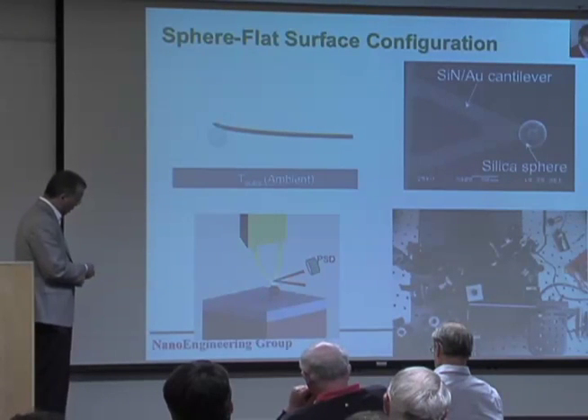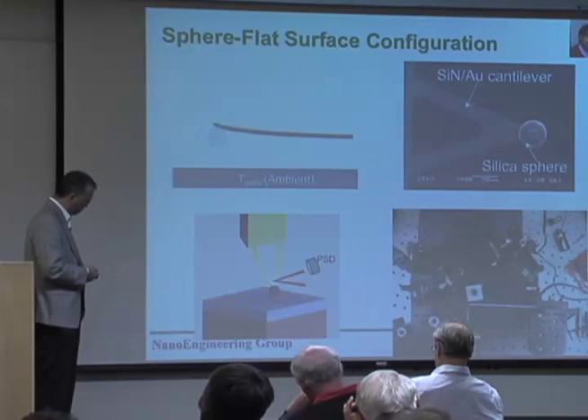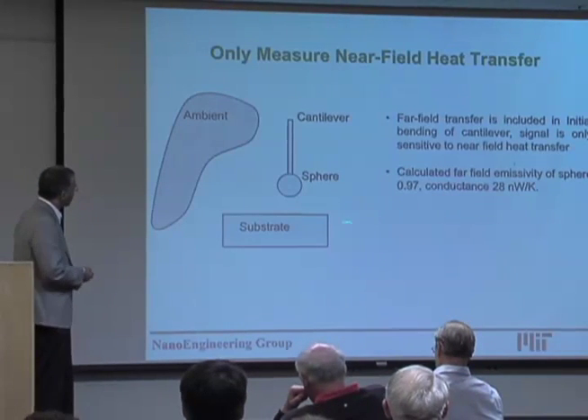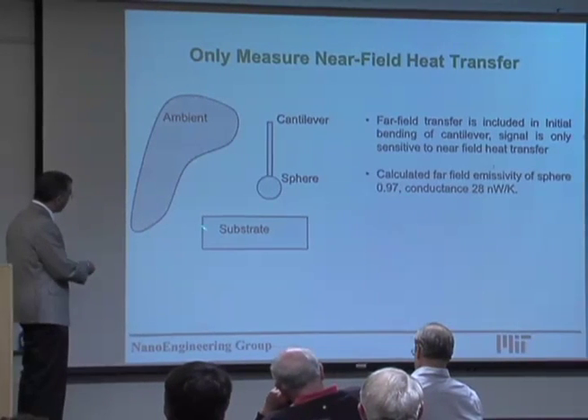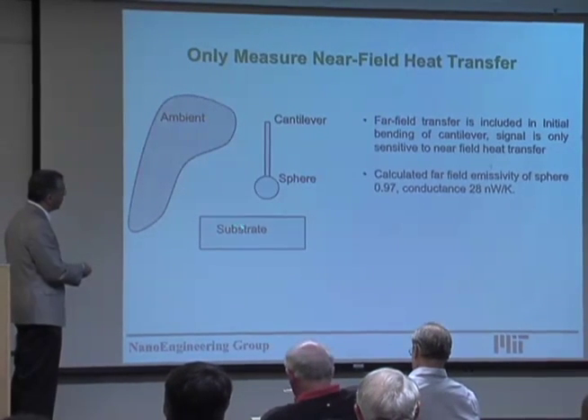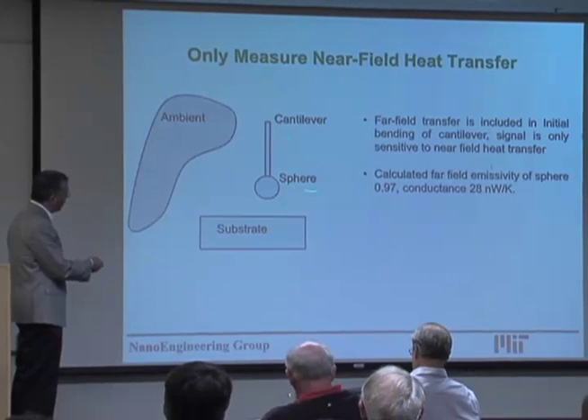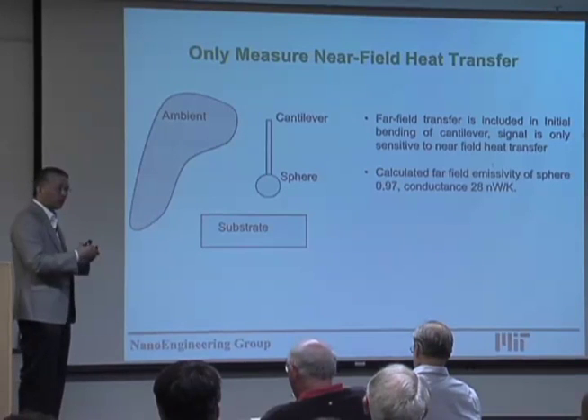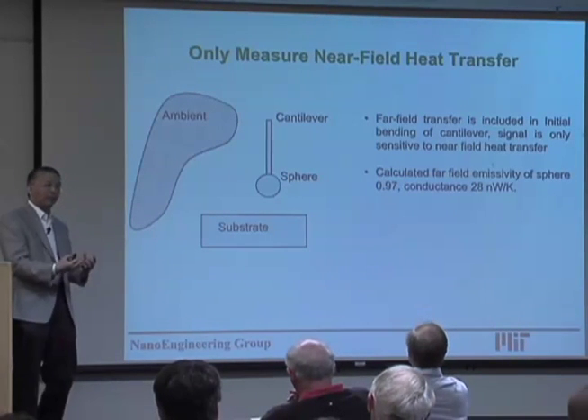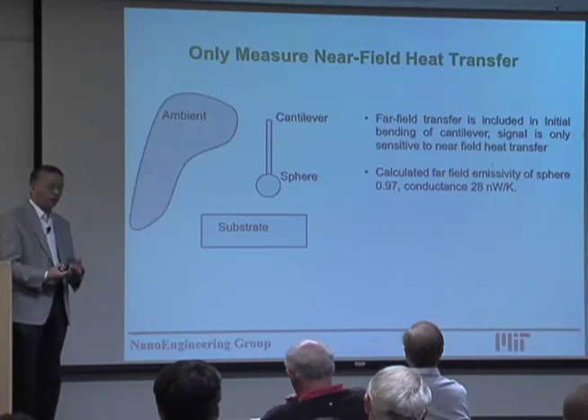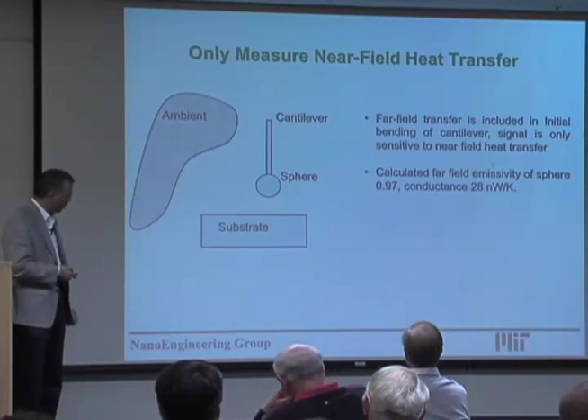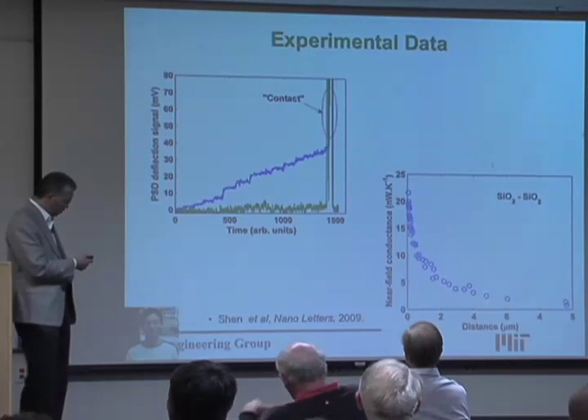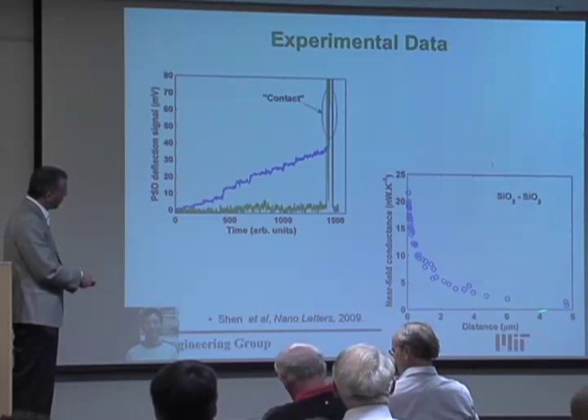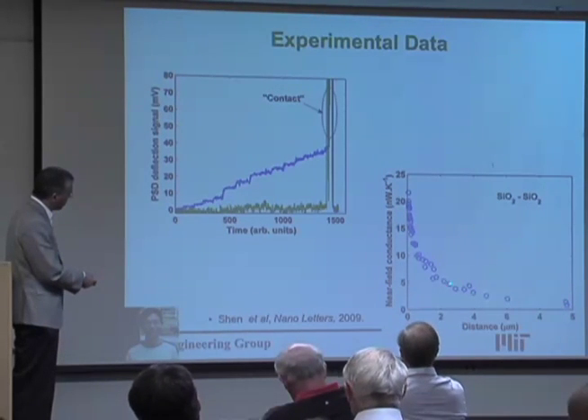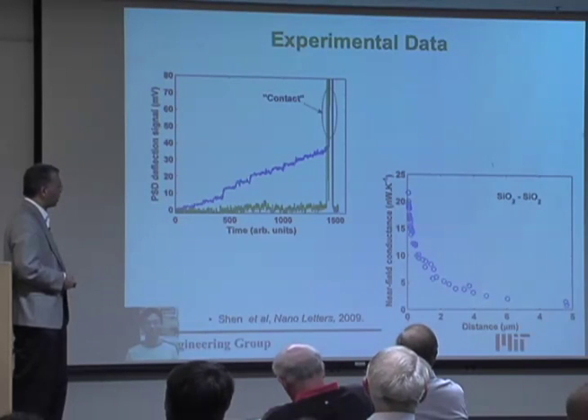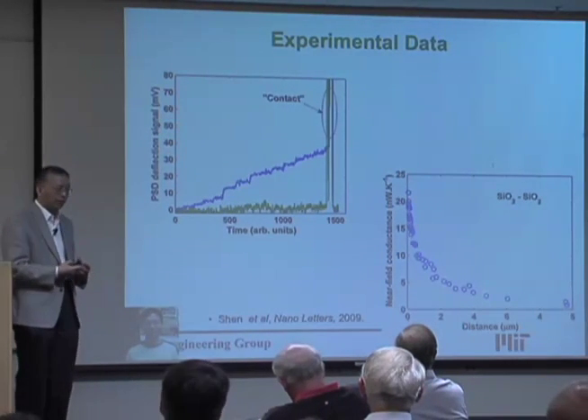So this is a heated cantilever. When you approach the surface, the near field will create the bending of the cantilever. If you do the analysis, because the surrounding is at ambient condition, we found that the initial bending is the far field, and the initial bending cannot be measured. So we really just measure the near field heat transfer, because the far field is a combination of conduction and radiation. So those were some of the data here. When we approach the surface, you see the conductance increase, and that's the near field effect.